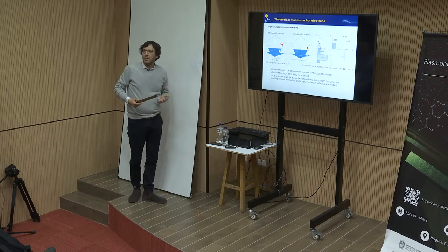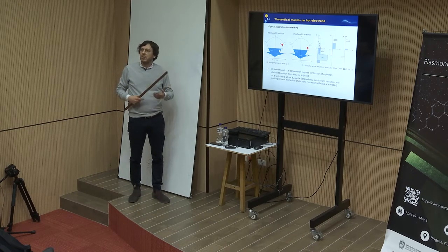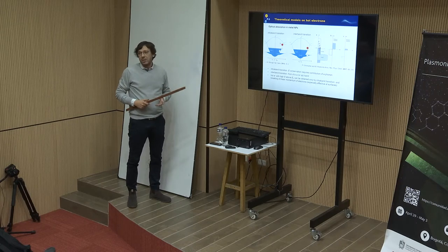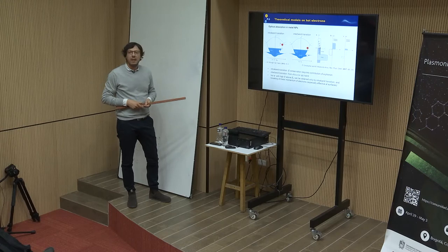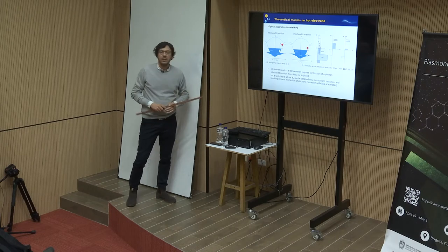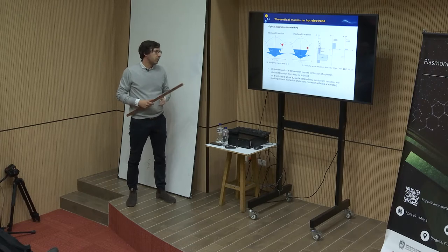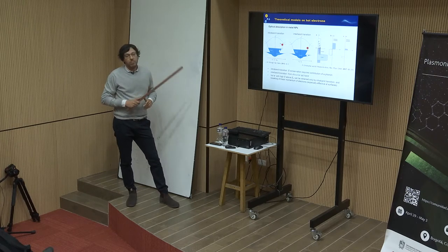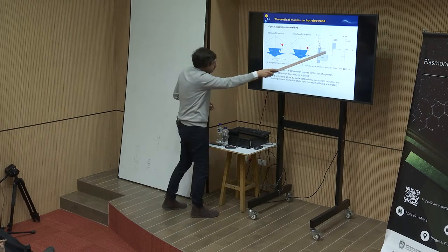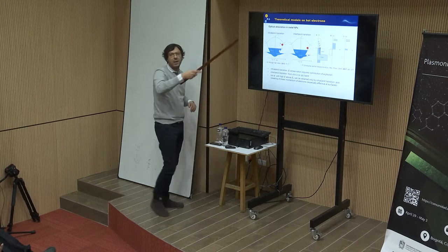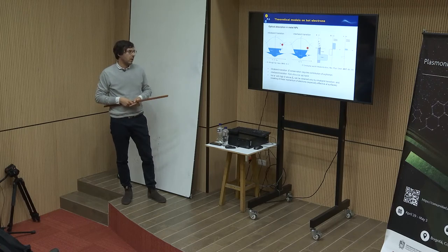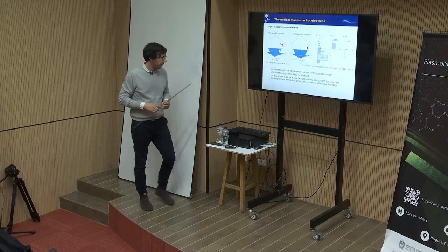And so if we need, for example, an application where we need a high oxidation potential, we can maybe use interband transition, but the electrons have very low energy, so we cannot activate highly demanding chemical processes, for instance. Otherwise, if we excite the conducting electrons, which belong to the sp band usually, in the excitation of the plasmon, we can create a distribution of hot electrons with energy much higher than the Fermi level, and so we can use these hot carriers, as they call them, to drive some interesting processes.